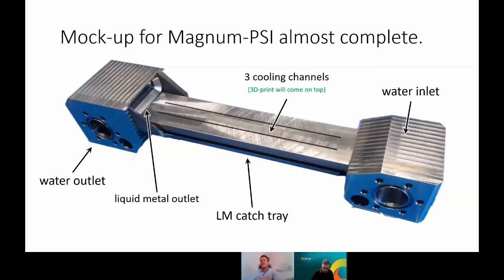Yeah. So in my mind, this indeed is a very open topic. So we have only hypotheses. I would say there can be some pros and some cons, right? The issue that you mentioned, that there could be pores in which the liquid metal could go and influence maybe the flow dynamics for the worse, that could be bad, but it could also be great, because now you don't have any open voids that reduce your thermal conductivity. And the same thing you could say about helium production, for example, right? There might be helium production, which leads to swelling and whatnot.